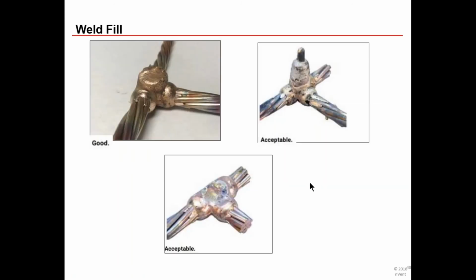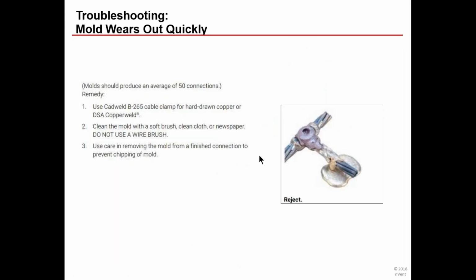Now we're going to go through troubleshooting of unacceptable welds and why it's happening. So here is the weld. You've got a whole lot of things going on. You have pitting going on here. You can see a lot of slag inside of that weld, and you have a lot of leakage. There are a lot of things going on here. If you're not using the right clamp or did not close it properly, did you clean it properly? Did you make sure it wasn't moist? Did you get all the grime? It won't necessarily feel moist, but there is water in there that you need to get out.